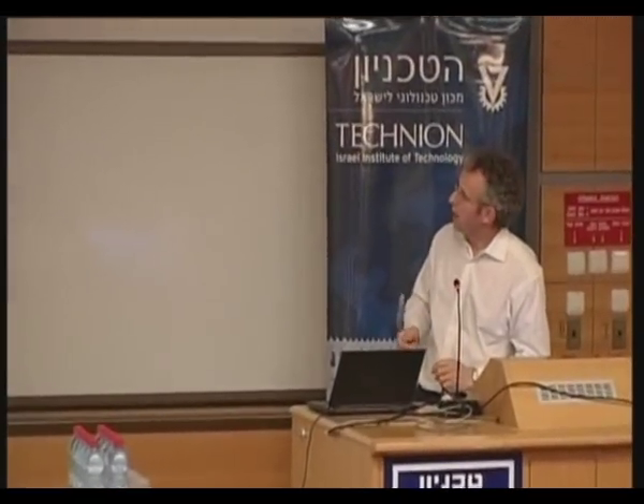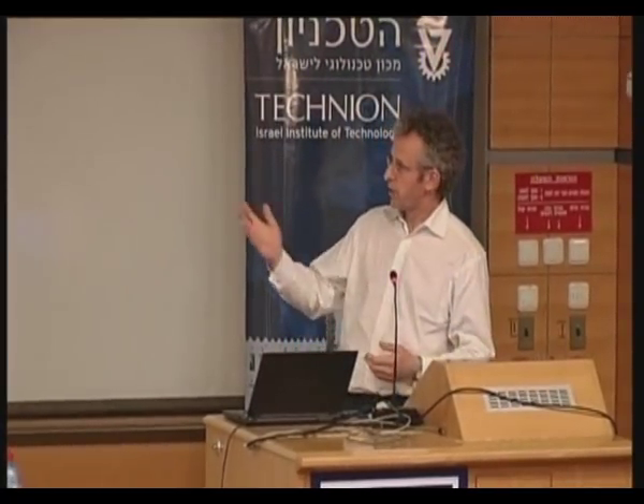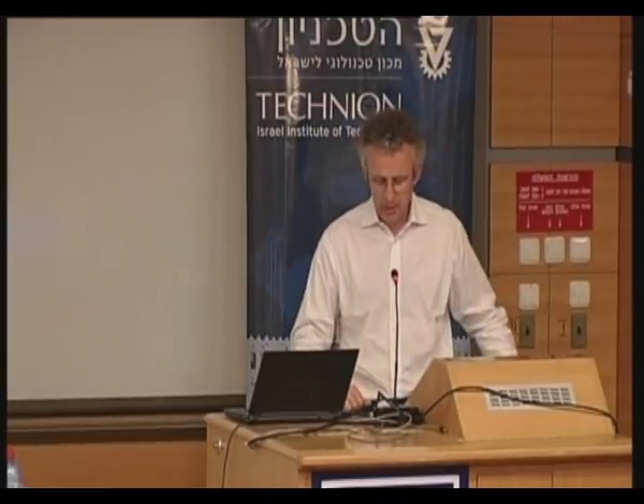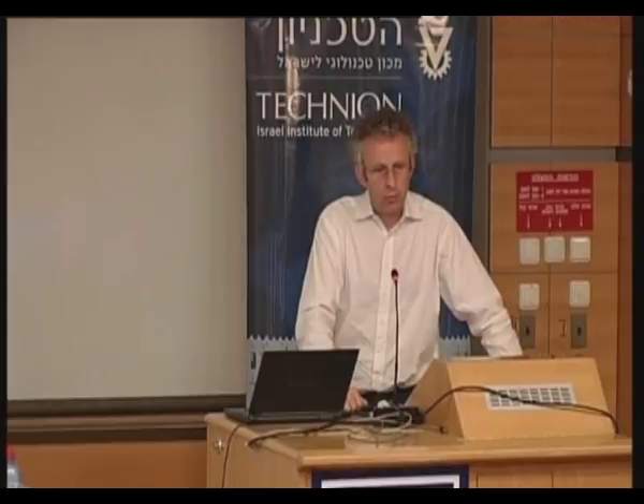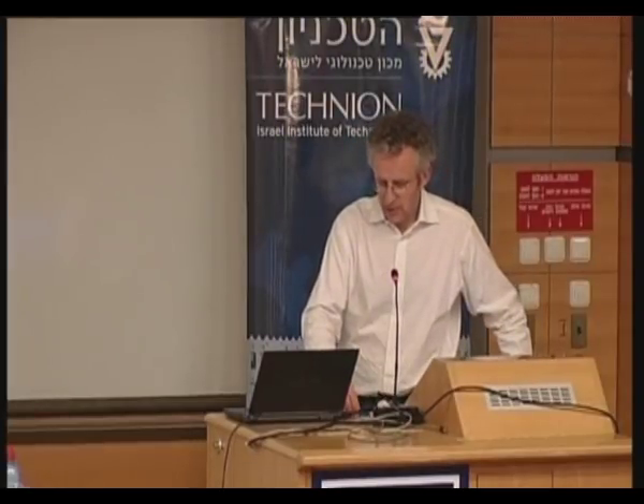One of the ways that you can form structures of this type is actually just to take two polymers, and here obviously they're hole-accepting and electron-accepting polymers, and mix them up in the same solvent and spin down, just, you know, paint down a film and pump the solvent out. And we make use of a well-known property that is something which is most of the time a nuisance, and that is that polymers generally won't mix.